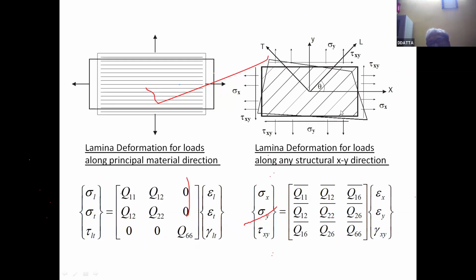If it is an arbitrary fiber orientation theta, then the deformation of the lamina will be arbitrary. Arbitrary in the sense that if it were a rectangle, after application of load, it will become an arbitrary quadrilateral, because there is everything. There is elongation, there is contraction, there is shear deformation. So a rectangle does not remain a rectangle, it becomes a quadrilateral. Whereas in case of principal material direction, a rectangle becomes a deformed rectangle. The shape does not change because there is no shear strain.